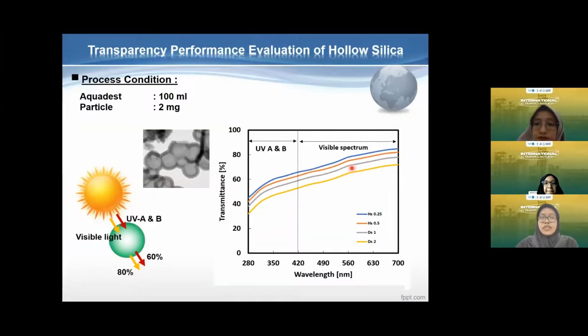For the hollow particles, we can use them for UV transparent materials. These materials can transmit around 60% for UVA and UVB, and for visible light, around 80%. So I checked the transmittance for these particles, and it is around 60% to 80%.